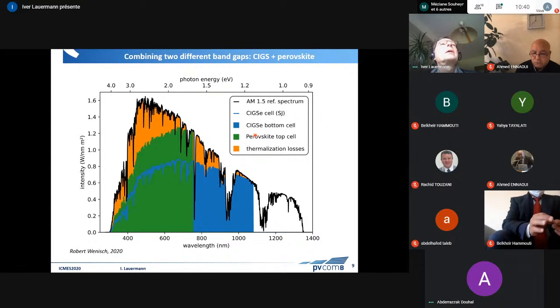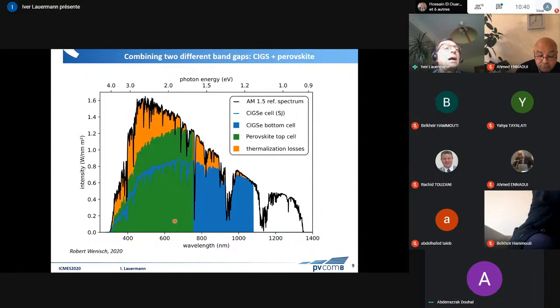If we look at the CIGS, which here we call the bottom cell because it has the lower band gap, the blue curve shows us the utilization of the solar power by a single material. And the green curve here shows us the utilization by the higher band gap perovskite material. So it starts at a higher energy at a lower wavelength. And now, if we combine these two, the blue part and this green part, we get the utilization in a tandem. So this is higher than just the blue part alone or just the green part alone.